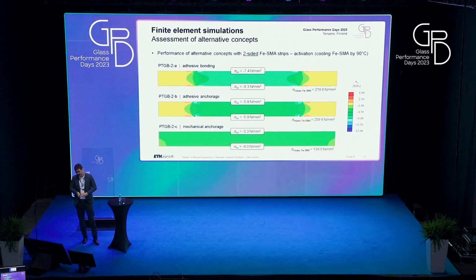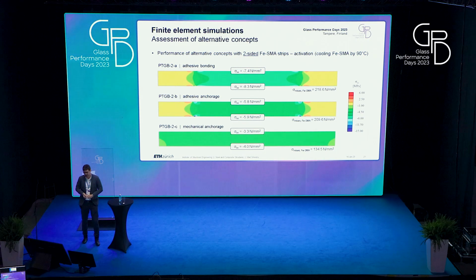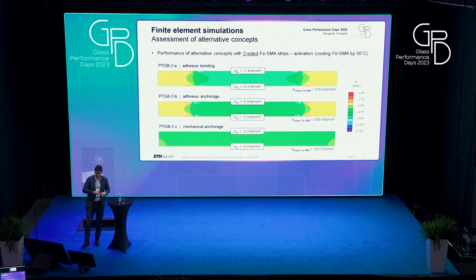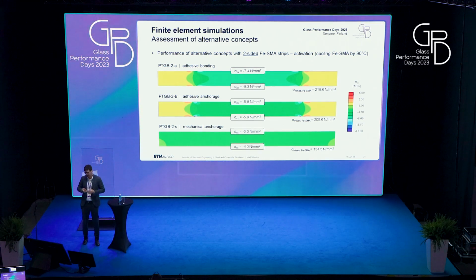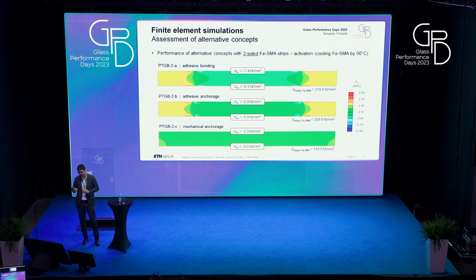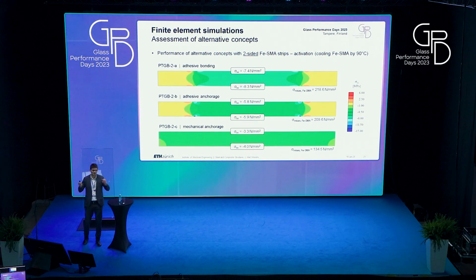If we look at the values, we can observe that actually the beams that we first tested experimentally with adhesive bonding along the whole length of the edges performed best. So there you can reach the highest pre-stress. For all these beams, the pre-stress was applied in the simulations by cooling, so we cooled them with the same temperature.